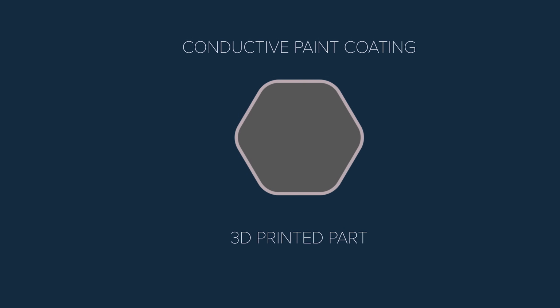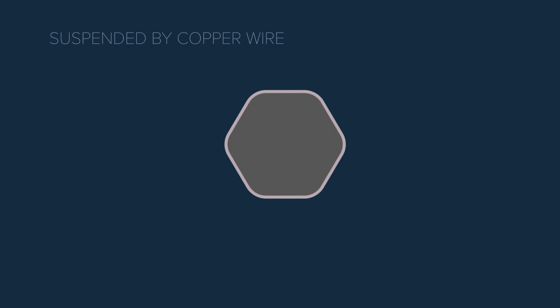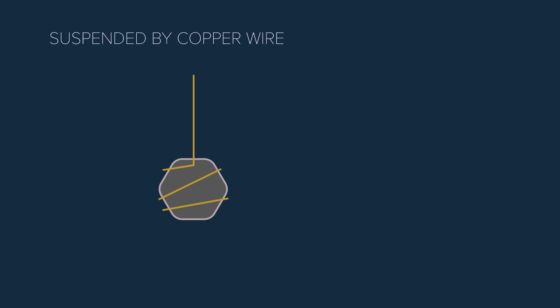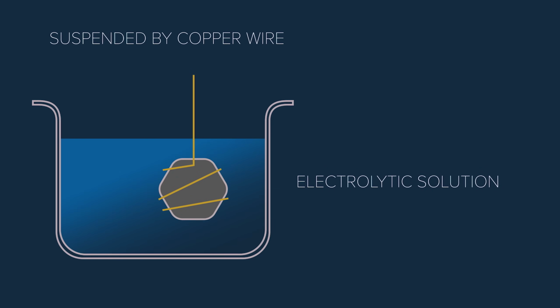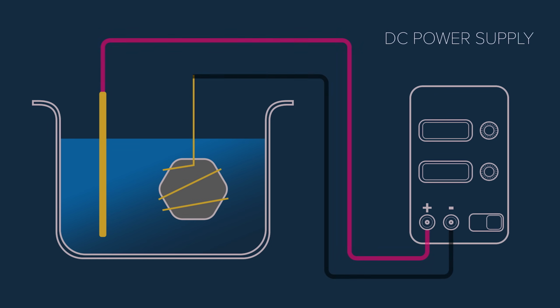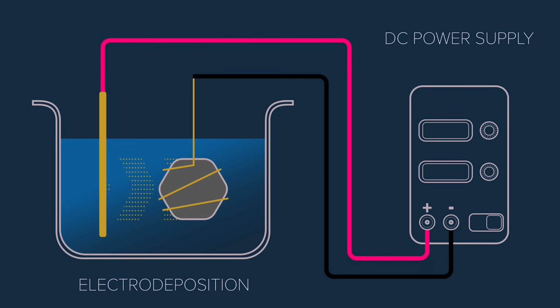First step in the electroplating process is to cover the 3D printed part in a conductive paint. The part's then suspended in an electrolytic solution. A metal anode is then placed in the solution along with the print. Whatever material this anode is made of is what will coat the part. In this case, I am using copper. When current's applied, the copper is deposited onto the surface of the 3D print. If everything's set up right, you'll get an even deposit of copper across the entire surface of the part.